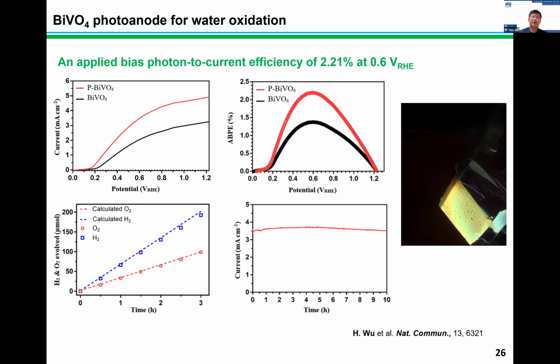But when we did this work, we found a problem: no matter how we optimize our samples, the experimentally obtained value for polaron hopping activation energy is always larger than that of the theoretical counterpart. Why is this the situation? Then upon investigation, we noticed that bismuth vanadate has many intrinsic defects, such as oxygen vacancies. And such defects can Coulombically interact with the negatively charged small polaron. So in this situation, it will drag the polaron and form the bound polaron.